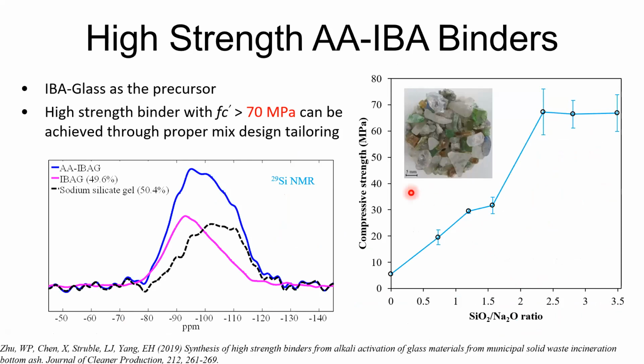With that understanding, we start to tailor the high-strength binder by only selecting the glass particles as a precursor. After doing the analysis and mix design, we're able to achieve a binder strength of 70 megapascal. However, NMR analysis shows that this type of alkaline activation of glass basically gives us a binder consisting mainly of sodium silicate gel, about 50%, with the remaining being unreacted glass particles.